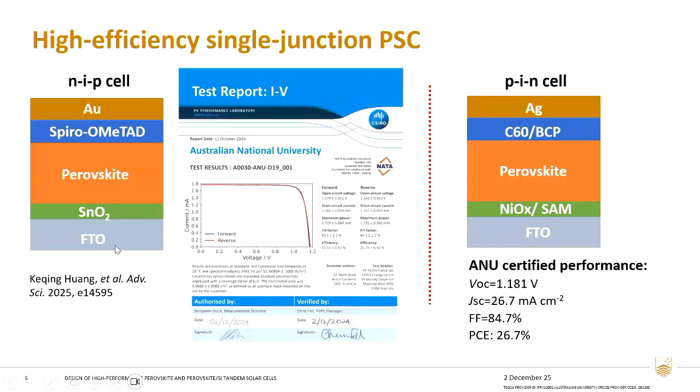That's one of the structures that our group at ANU has been researching for around one decade, and one of the typical IV performances is shown here, which is one of the high performances we recently achieved in the last year, where we get over 26.7% efficiency from the reverse scan. That represents one of the highest efficiencies based on the same structure.